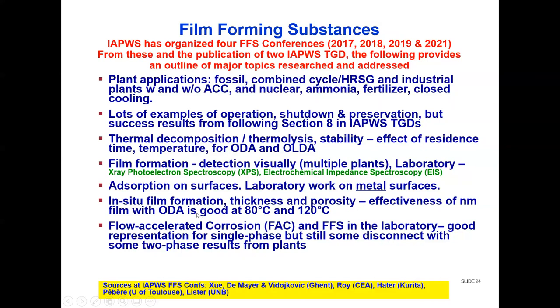And we find that there is good performance up to these temperatures, and porosity is one of the things that we have to avoid. There's some work done on FAC in the laboratory, but unfortunately, as the air-cooled condenser environment is two-phase, the results of those laboratory experiments are not as good for the two-phase situation.